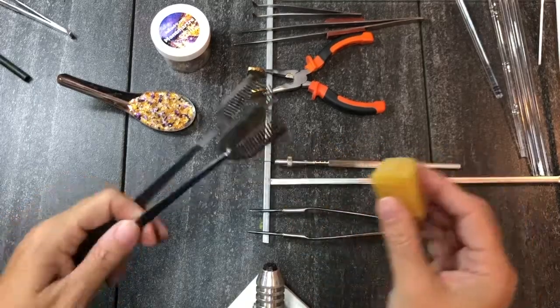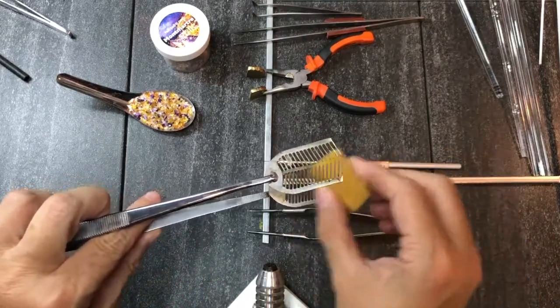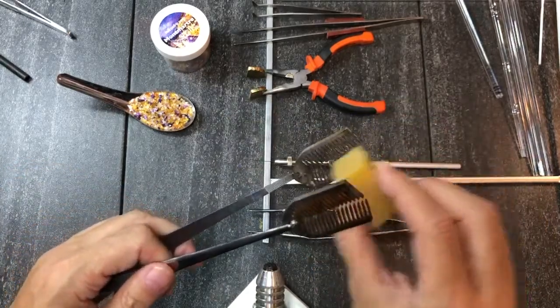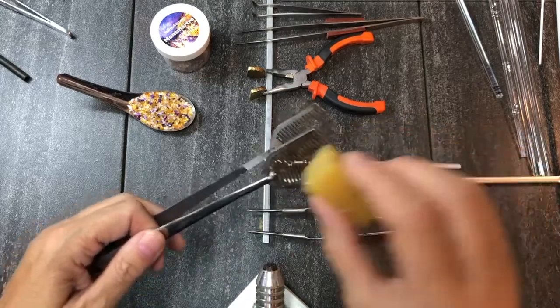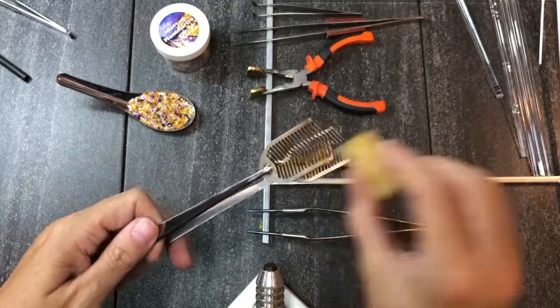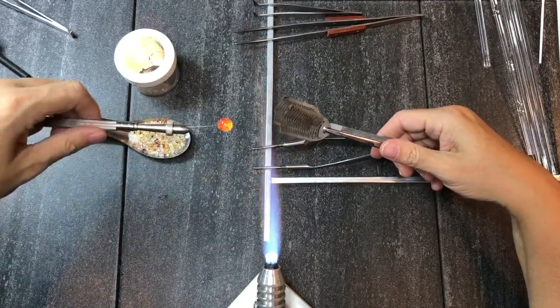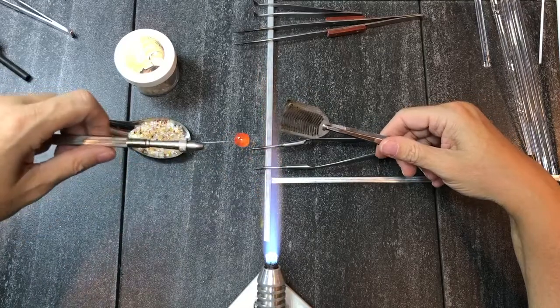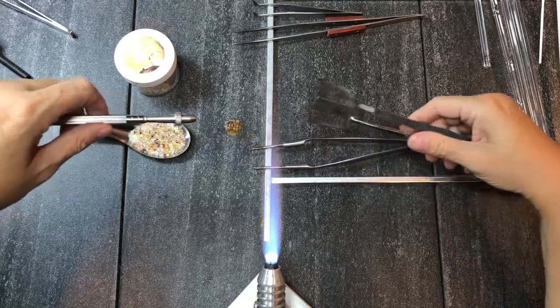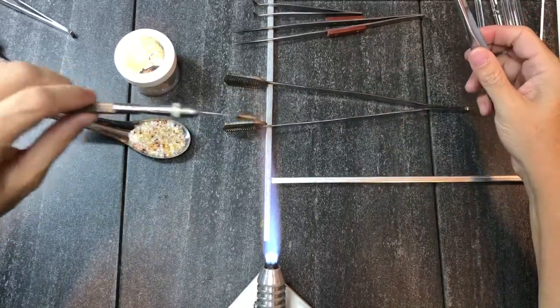Before I start to use it, I'm just going to rub a little bit of beeswax on the surfaces on the inside. I don't want to put too much — not trying to glob it up, just get a very light loose coat. The edges and the points are where the glass tends to stick if it's going to stick. Before I sit down to use it I'll just wipe a little bit on. You have to let a bit of a skin form first. If you put this all in here too hot it will stick to these tongs, especially the small one which is the one I'm using. So let a bit of a skin form, center that, and give it a quick press and release. You might have seen a little puff of smoke — that's from the beeswax, and that helps keep it from sticking.